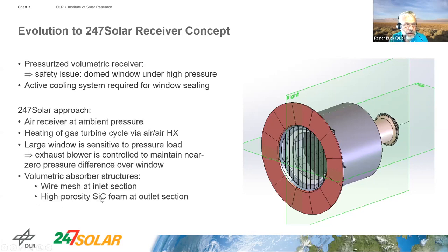So based on these reasons, 24/7 Solar developed its own approach with an air receiver, a volumetric air receiver at ambient pressure. And the heating of the gas turbine cycle is then done by an air-to-air heat exchanger. The large window that is intended to be used there is, of course, sensitive to pressure load. So for this reason, an additional exhaust blower is used to control the near zero pressure difference over the window to keep the window in stable operating conditions. And then we use volumetric absorber structures, as we did in previous receiver designs, wire mesh at the inlet section, because there we operate at lower temperatures, and the high porosity silicon carbide foam at the outlet section.